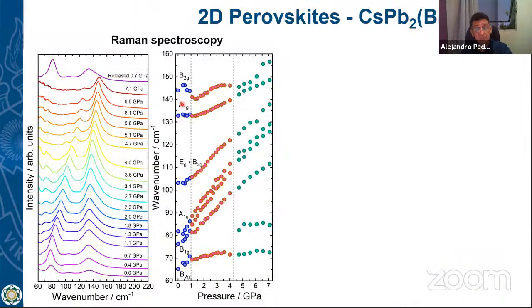We study Raman spectroscopy, and now we are doing Raman spectroscopy under pressure. To apply pressure, a tiny sample is placed between two diamonds with a liquid just to induce hydrostatic pressure. And these diamonds are forced to go one towards the other, in order to reach very, very high pressure.